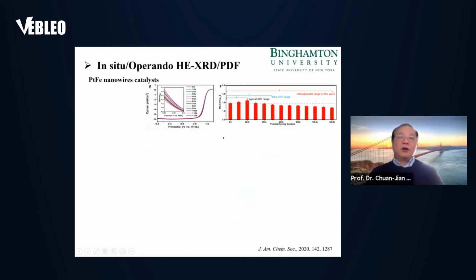All right, so this is the final set of data for this first part, the nanowire. We're using a platinum iron nanowire catalyst, putting the load in the fuel cell. This particular catalyst has very high activity as illustrated here, and is also very stable for up to 120K cycles. The activity only drops about 30%. That's truly remarkable for this type of catalyst.